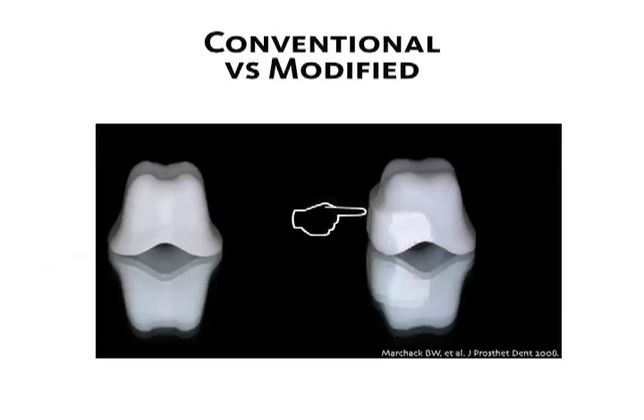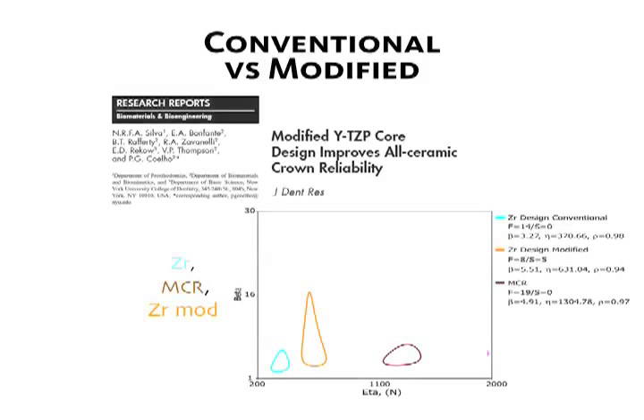It has been suggested in the past that framework design modification, here seen as the addition of a lingual collar that extends to both proximal areas, would help improve porcelain support, so we have looked into that in a subsequent fatigue study. And the results have shown that the modified zirconia framework crown was significantly stronger, as we can see by the positioning of the orange contour towards the right-hand side compared to the conventionally designed framework zirconia crown, but still significantly lower than the metal ceramic.